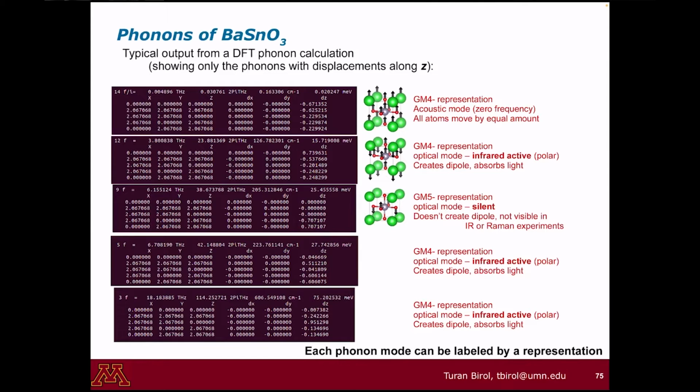And what can be done is, it turns out that you can assign a space group irrep. Irrep means irreducible representation, which I will just call representation from now on because we won't talk about reducible ones separately. You can assign a representation to each phonon mode that determines its characters, just like the different vibrational patterns of the carbon dioxide molecule we used before.